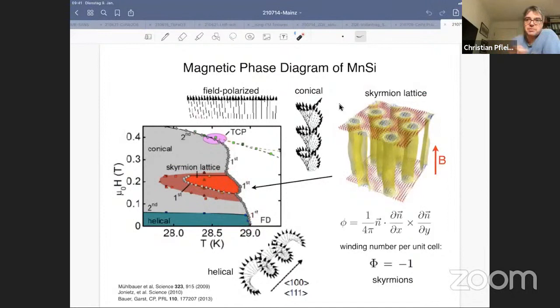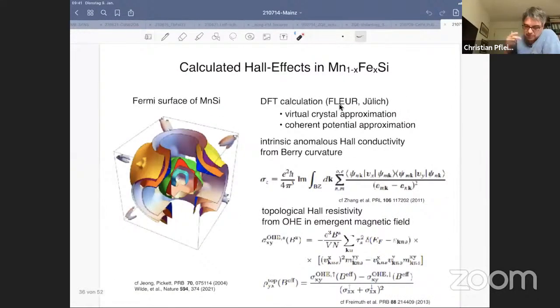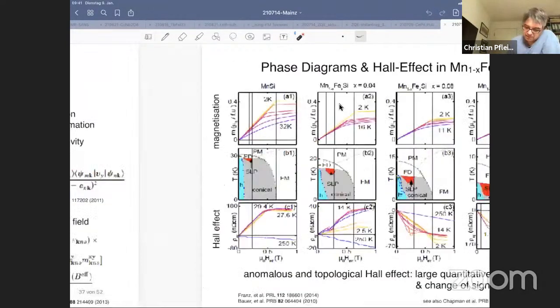When you do transport measurements, you want to have an ab initio explanation for this Hall effect that you see, or these fancy phenomena. So we did some studies where we measured the Hall effect in a series of manganese, iron, silicon. And Frank Freimuth, Yuri Mokrousov and Stefan Blügel did DFT calculations using FLEUR of the anomalous Hall conductivity, the Berry curvatures and this topological Hall signal. Right, so I'm going to just skip this slide here.